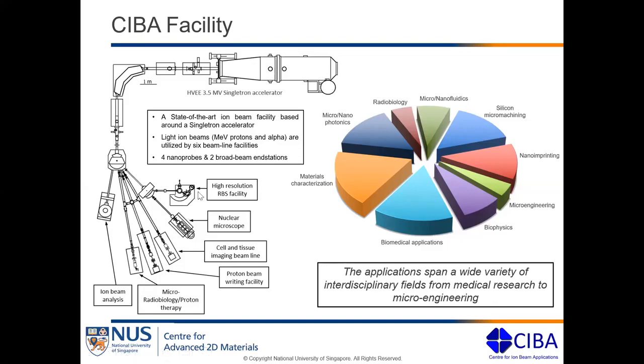The next and last beamline is called the high resolution RBS facility. RBS means Rutherford backscattering spectrometry. In this beamline, we have ultra high vacuum conditions where you can do compositional analysis of very thin samples. For example, the depth resolution of this beamline is less than 1 nanometer, so you can actually do a composition analysis of a sample less than 1 nanometer thick.